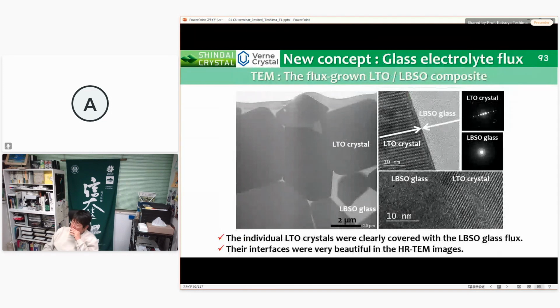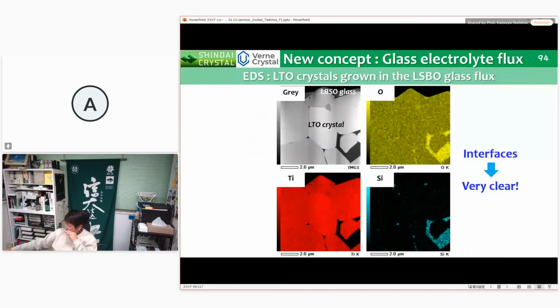These pictures show the flux-grown LTO-LBSO composite. The individual LTO crystals were clearly covered with the LBSO glass flux, and their interfaces are very beautiful in the high-resolution TEM images. As with the LCO composite, the LTO-LBSO interface was very clear, as shown in this EDS mapping.